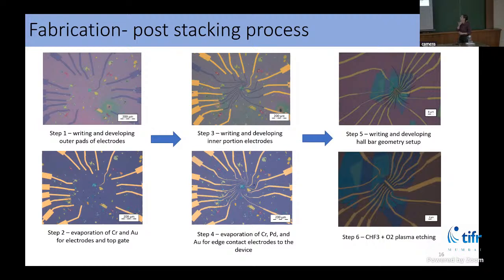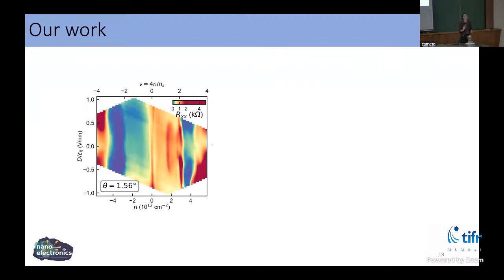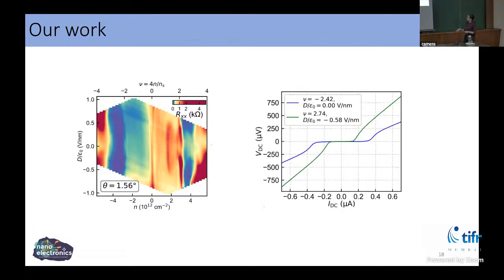And okay, I will come to that part later. So in our work, when we have a device ready, the next step is to measure it. We usually cool it down to millikelvin temperatures, and we make a similar plot where we map the resistance of the device as a function of doping and electric field. Similar to the plot that I showed you before, I also see zero resistance in 2 pockets of the device. If I do DC IV measurements to characterize these superconductors, the blue curve is for the hole-side doped superconductor. The superconductor shows a zero voltage drop up to a point where it crosses to a non-zero voltage after this current, which is the critical current of the superconductor.